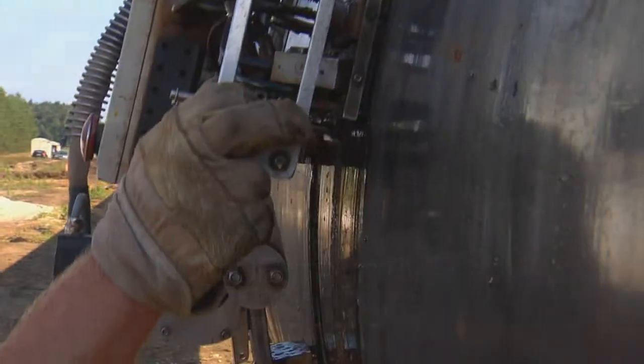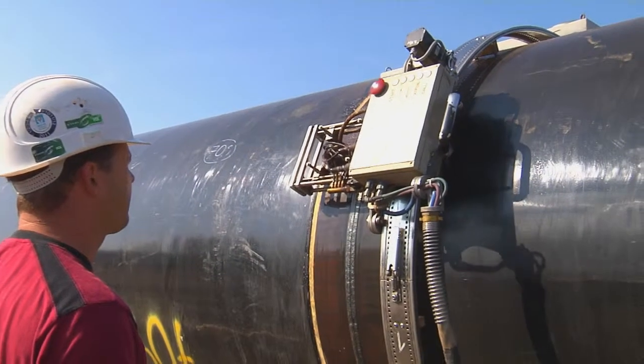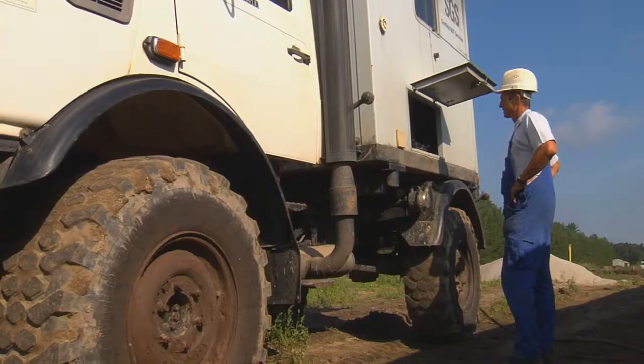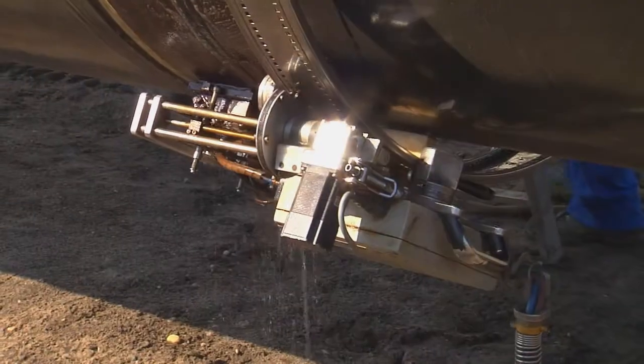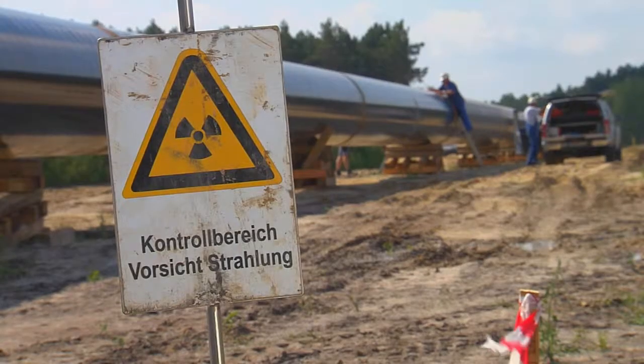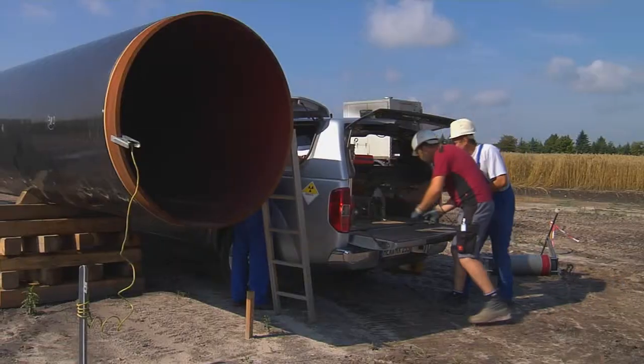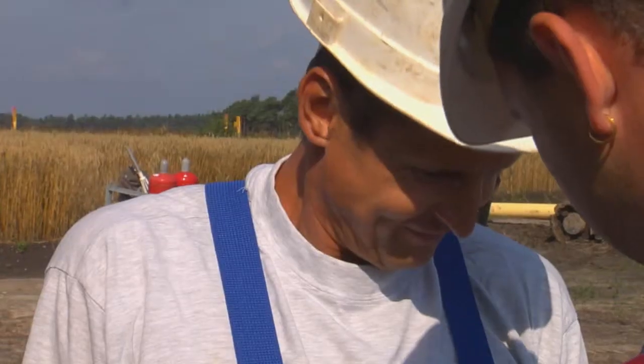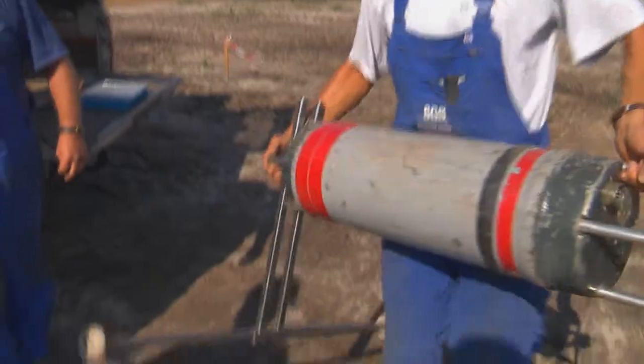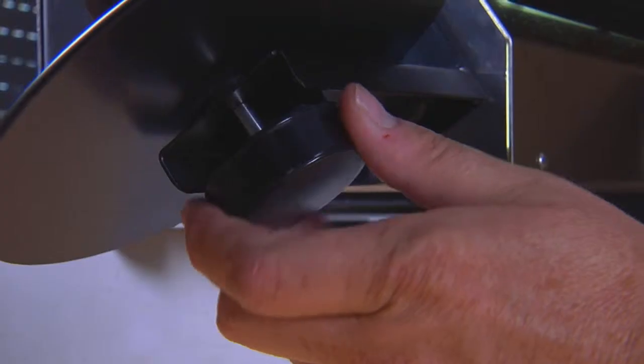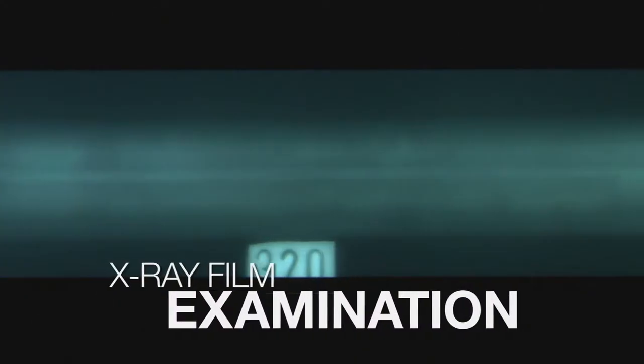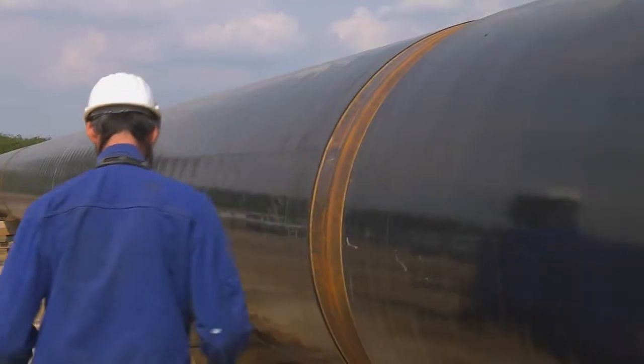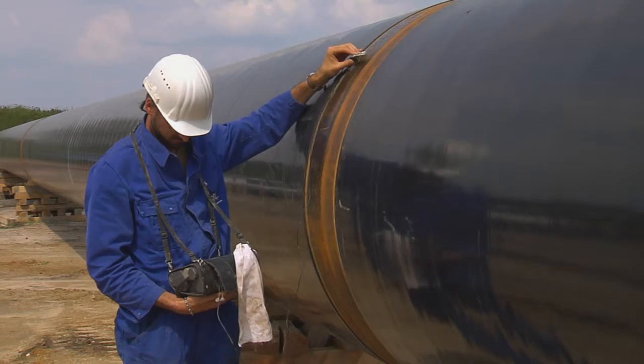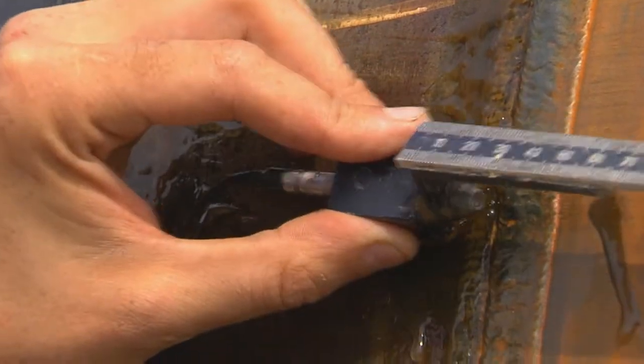All the seams created in the preliminary work are checked using a mechanically guided ultrasonic scanner. Approximately 30% of these preliminary construction seams are additionally irradiated by an X-ray tube. The results of these tests are meticulously examined by our expert appraiser, seen here studying the X-ray film. When examining the guaranteed seams, an additional ultrasonic test with a handheld sound source makes double certain.